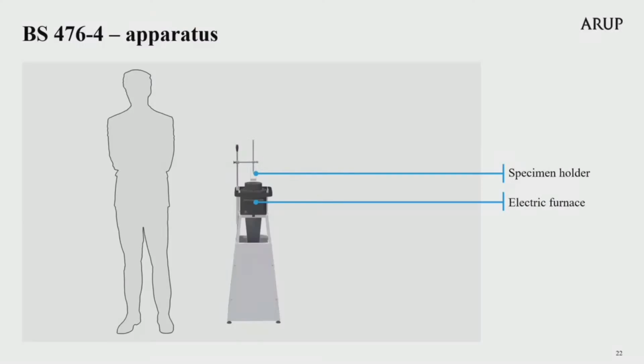The test apparatus for the Part 4 tests consists of an electric furnace which is switched on until the furnace temperature reaches a constant 750 degrees Celsius for 10 minutes prior to the test. A cuboid sample is placed in this furnace. The furnace temperature is measured by a thermocouple, positioned so that its hot junction is 10 millimetres from the wall of the furnace and at mid-height of the specimen. A thermocouple is a device for measuring temperature.